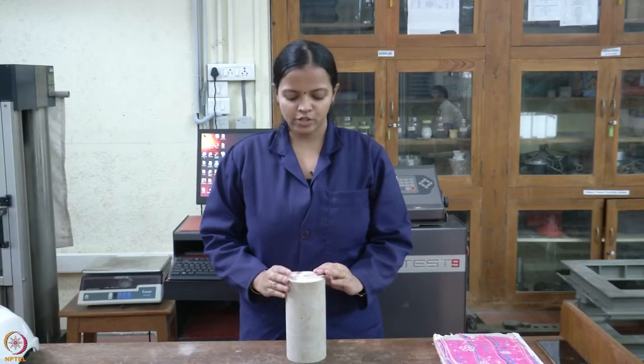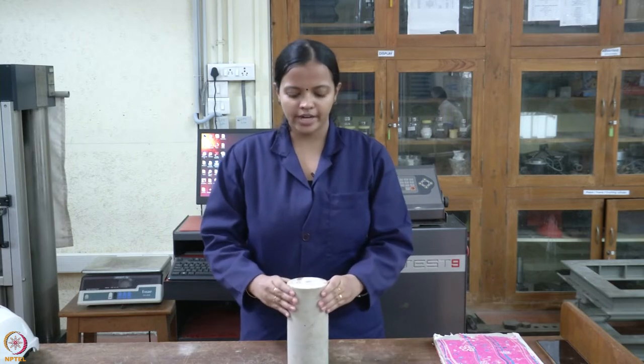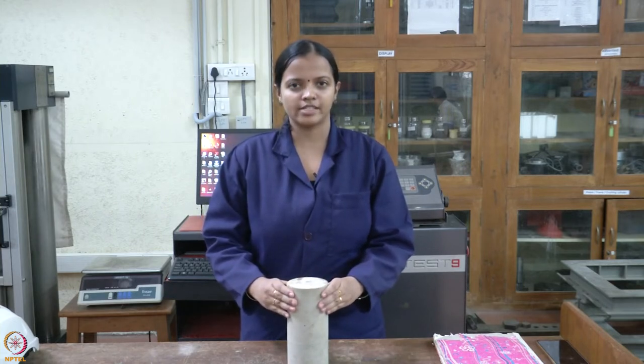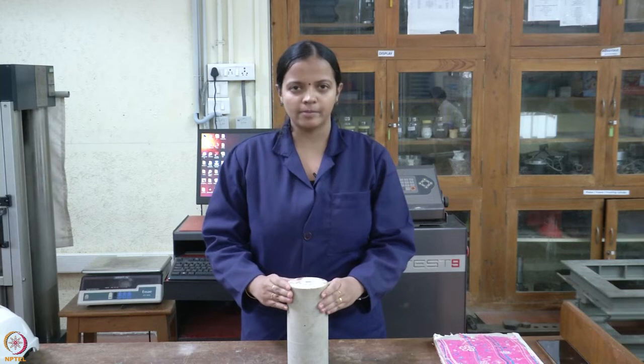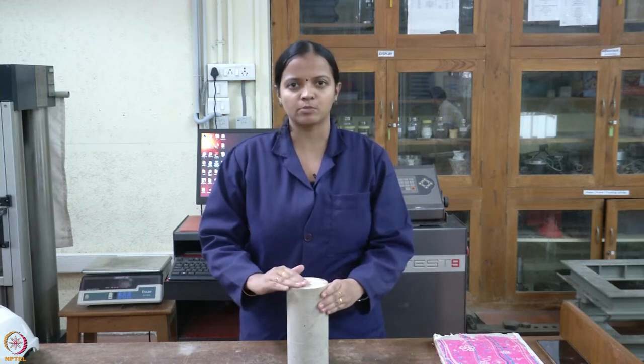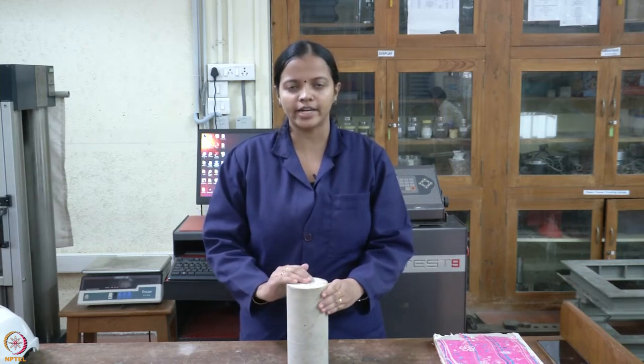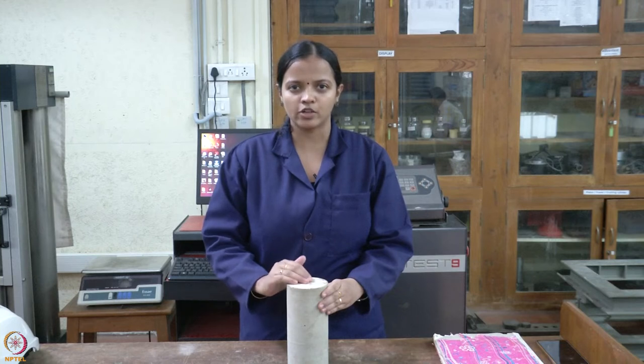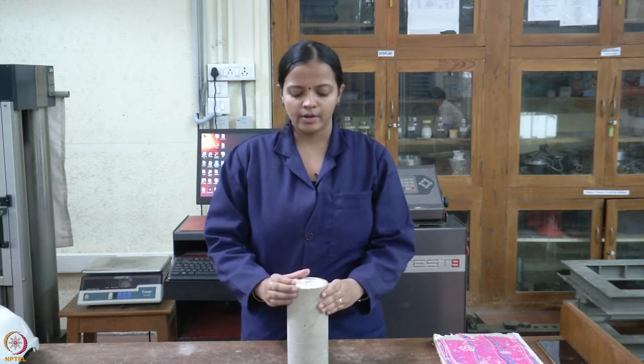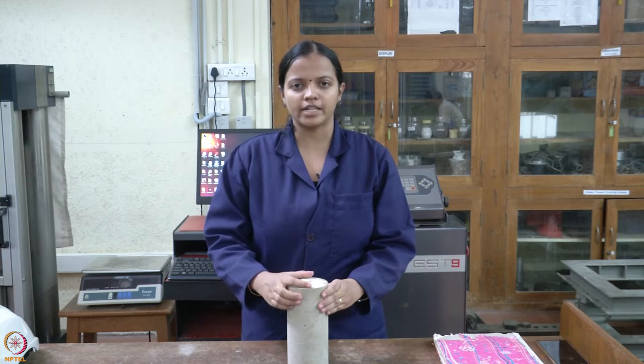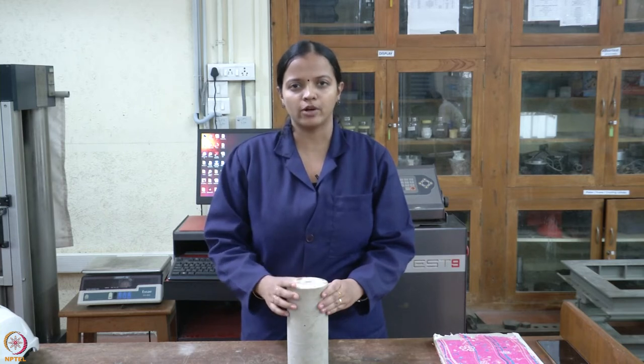The specimen should be ground or capped before testing in order to make sure the surface is smooth. Otherwise, there will be irregularities in the specimen because of casting, stress concentration might occur, and you won't have uniform loading on the specimen.